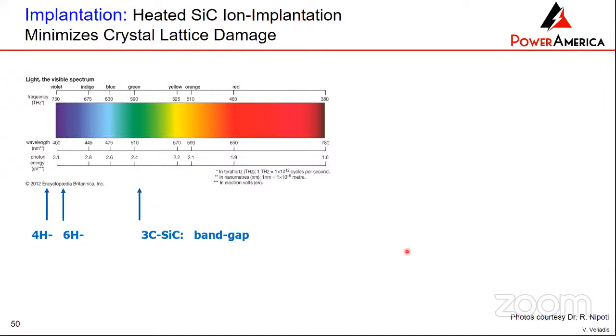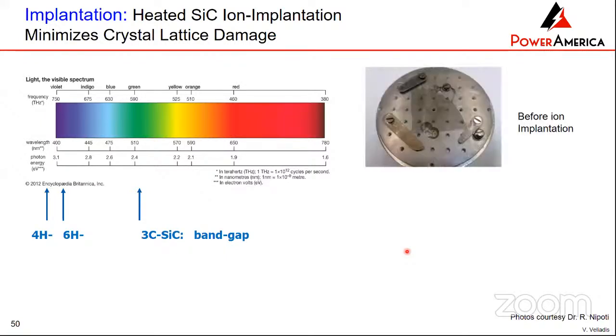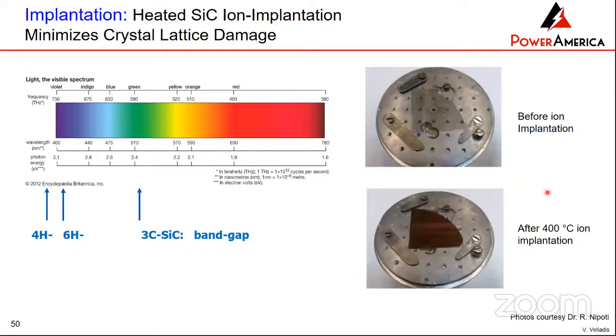In silicon carbide, implantation has to be heated in order to minimize the crystal damage. You can see this is a silicon carbide piece of wafer before implantation, and you can see that it's transparent as expected. After you do the implantation, where you have this bombardment of ions, the wafer looks like this, okay? So you've basically destroyed the crystallinity of the wafer.